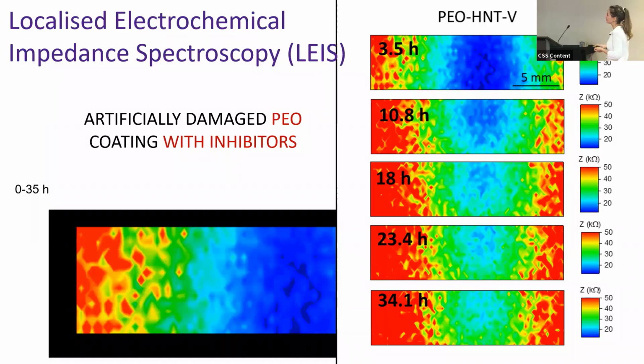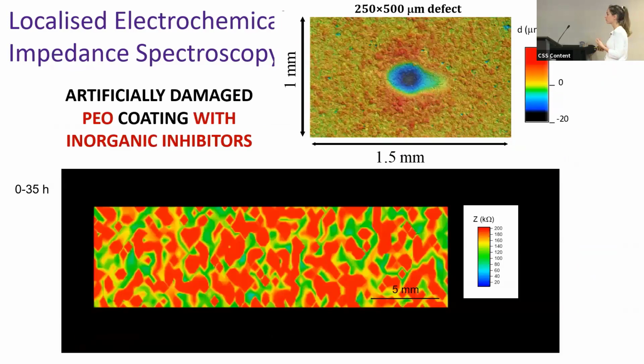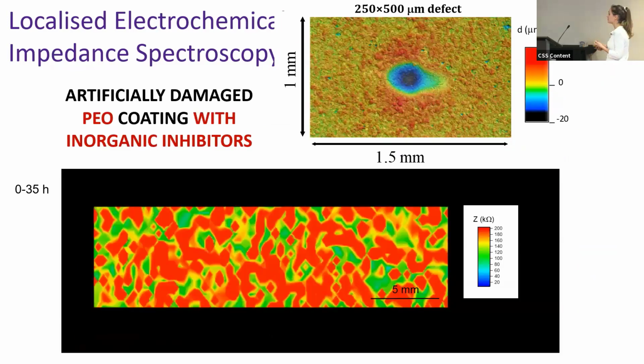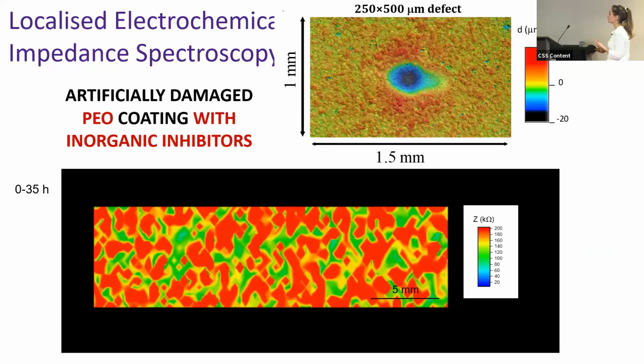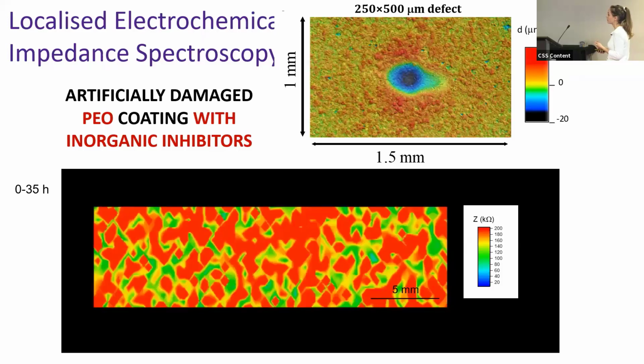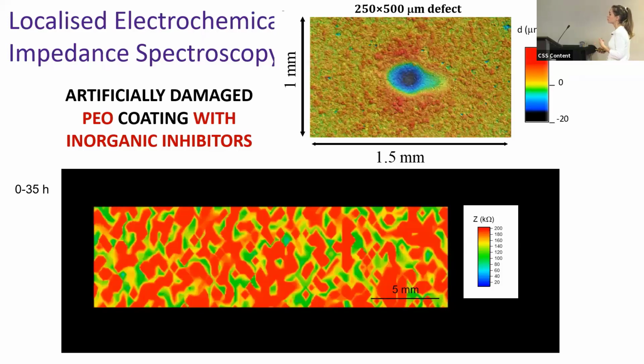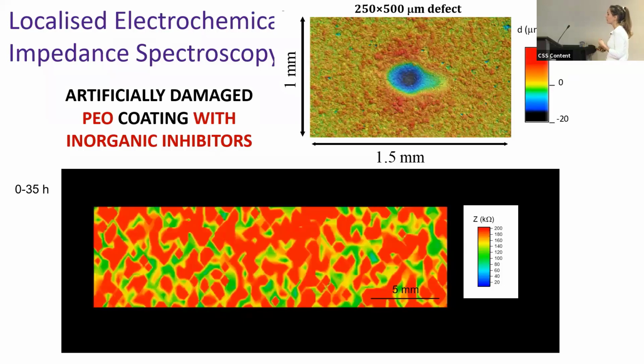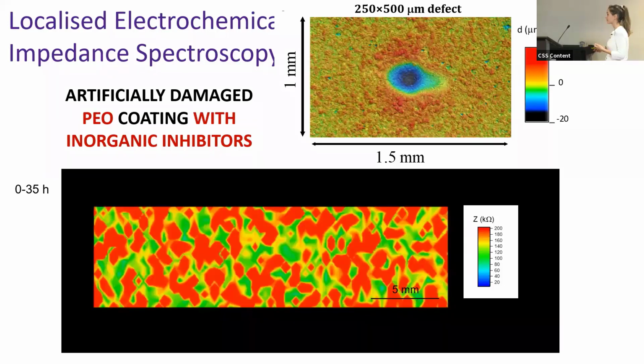We can also see that the size of the defect was considerably reduced after nearly 35 hours of experiments. In this case, we didn't manage to obtain a full recovery of the coating, and it's probably due to the large size of the scratch. So we decided to assess the self-healing properties using a smaller scratch. In this case, we couldn't even identify the defect at the very beginning of the experiment. So this means that the defect was probably completely self-healed after the first scan.